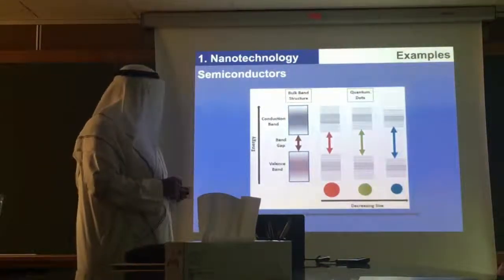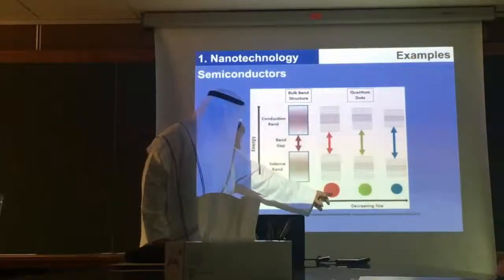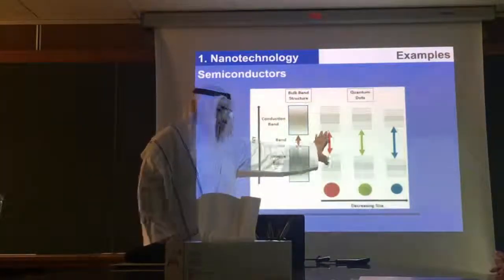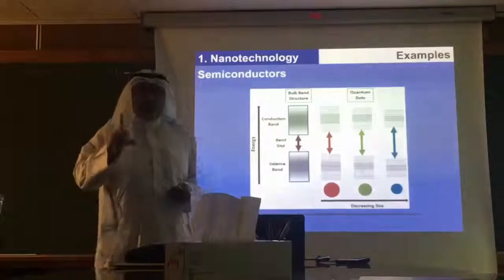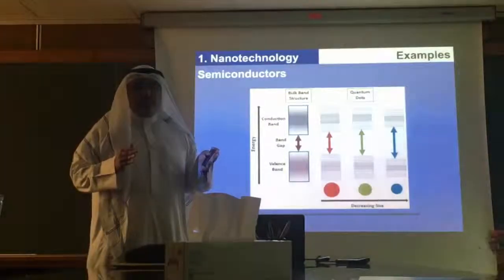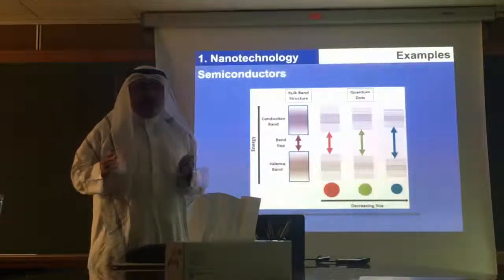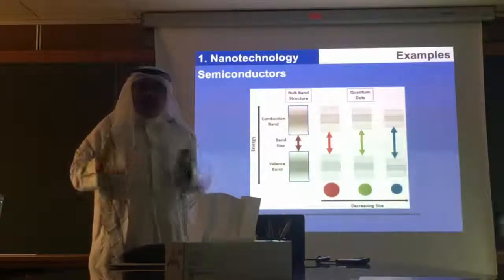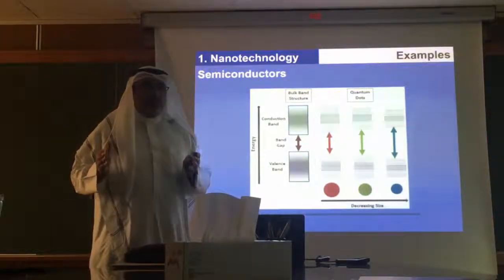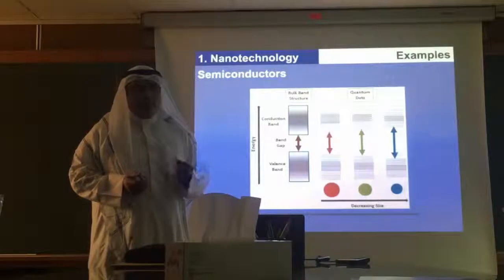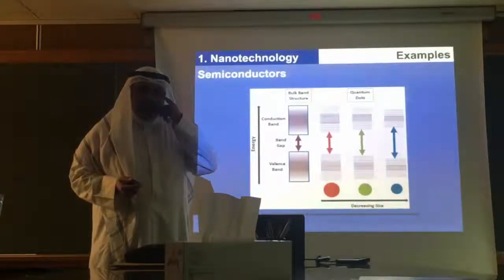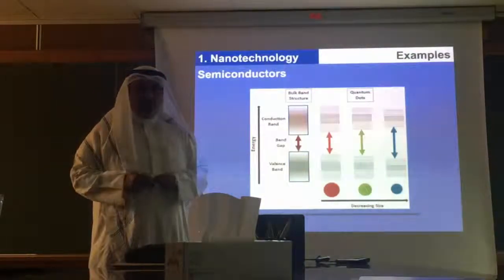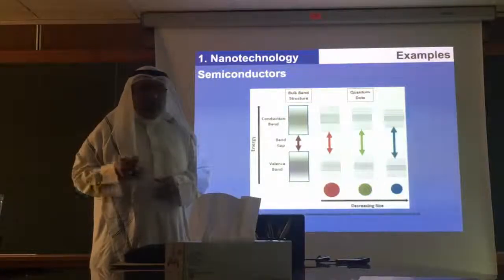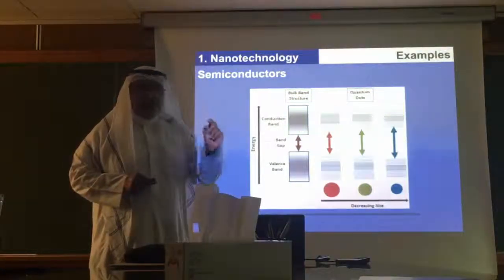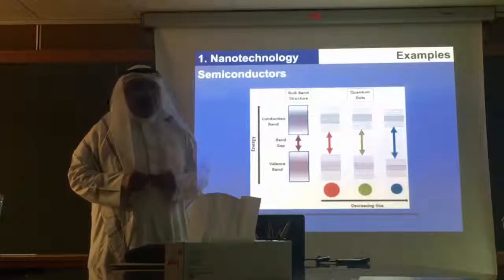So if I can make the titanium dioxide smaller, I can increase the band gap. And by controlling the band gap, I can shift the absorbance of this catalyst, or photocatalyst we call it, from the UV to the visible. And this is very interesting because if you can make our catalyst react with breaking down, for example, organic pollutant, just by decreasing its size, this would be very interesting.